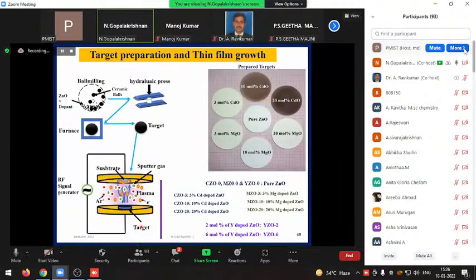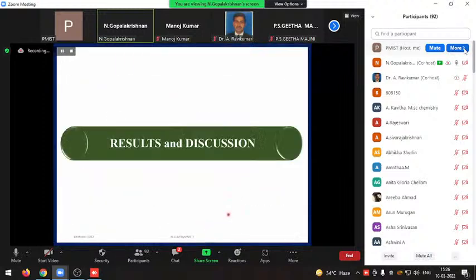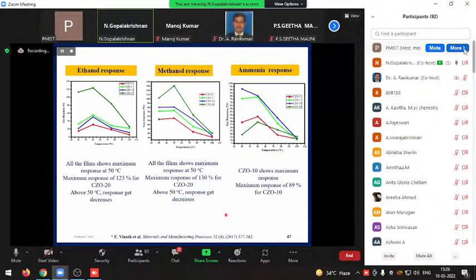Yeah, here I have shown CZO-3, which means 3 mole percent cadmium dopant, CZO-10 means 10 mole percent cadmium dopant, and CZO-20 means a 20% cadmium-doped film. That is what I have shown here. So here I have shown, for different temperatures and different doping, the control of the gas response.